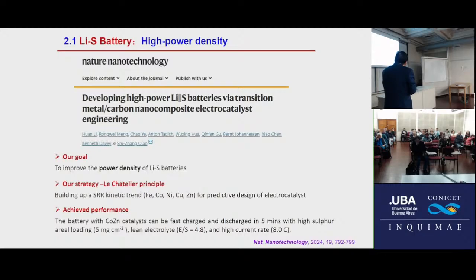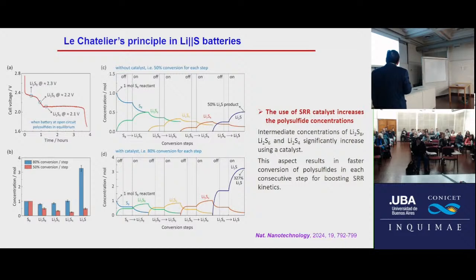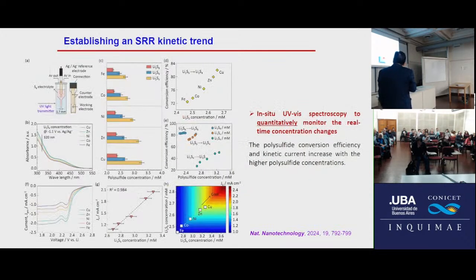So you can see in our case, very high sulfur areal loading and lean electrolyte, because this is a commercial condition. Here you can see in the battery there are actually different reactions at different voltages, with different polysulfide products. If we don't use a catalyst versus after we use a catalyst, you can see the conversion rate increases significantly. This one is quantitative.